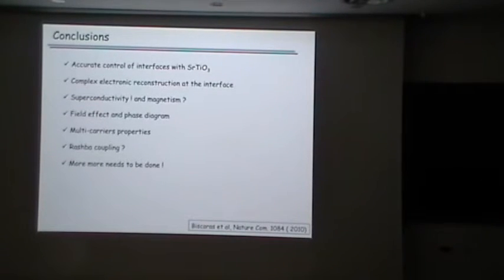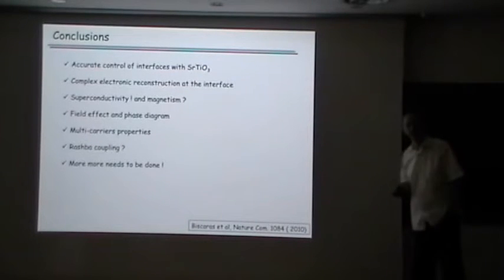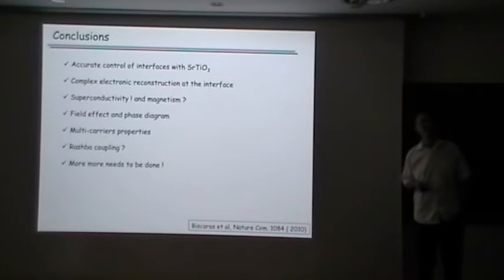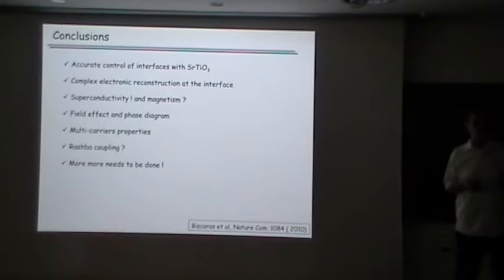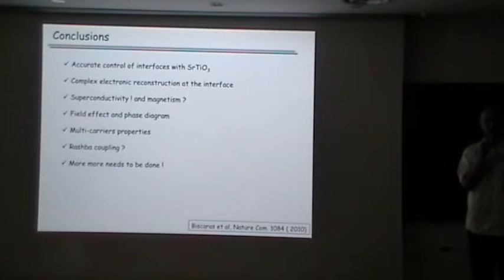The field effect and the phase diagram is potentially very interesting. Once you have understood what's going on, especially for the gas, because as I tried to convince you, when you put the gate voltage, you don't put only electrons in the system, of course, you change it drastically. And remember, I told you that in all the calculation of the orbitals, just at the interface, there is a gradient of the occupancy of the orbitals within the 1 or 2 nanometers.